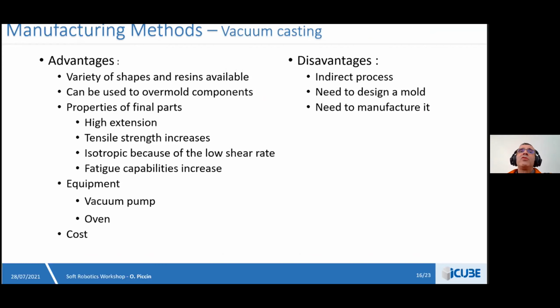So another experiment we have conducted was to use another process, vacuum casting, which has different advantages. One advantage is the variety of shapes and resins that you can find on the market. In fact, it's a myriad of resins, so it complicates the choice, but you have a very large choice. You can use this technique to overmold components. This is important, as I already said. Properties of final parts are predictable and can be easily repeated from one fabrication to another. The equipment is quite limited. You have just a vacuum pump and one oven to carry out the process using this method. So this is relatively low cost compared to the previous method.